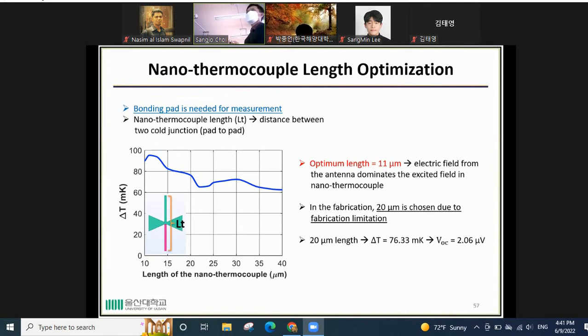It's showing a higher temperature difference because of the electric field from the antenna units, the excited field in the nanothermocouple. However, in the fabrication, because of the fabrication limitation, we choose 20 micrometers for the nanothermocouple length. So in our simulation, 20 micrometer length provide a delta T of 76.33 millikelvin, which corresponds to 2.06 microvolts.